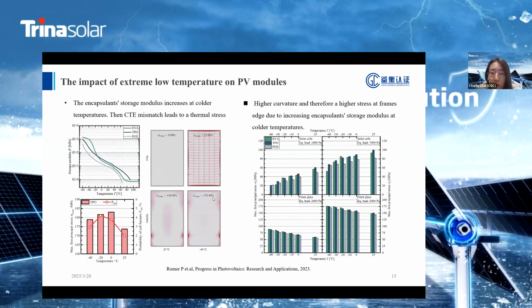Besides the homogeneous snow load, low temperature may cause embrittlement of the adhesives and further reduce stability. The encapsulant storage modulus increases at colder temperatures, thus it deforms less at the same load. Moreover, the CTE differs between the frame and front glass. This CTE mismatch leads to a thermal stress in the front glass. Higher curvature and therefore a higher stress at frame edge due to increasing encapsulant storage modulus at colder temperatures.